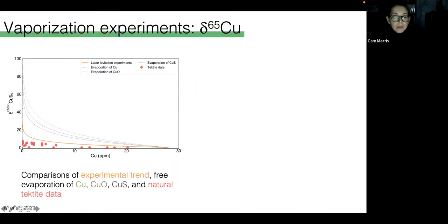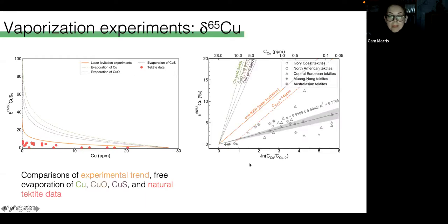So now I'm showing you again copper concentration on the x-axis versus delta 65 copper on the y-axis. You've seen all of these data before, I'm just comparing them. So now the experimental data is represented by this orange curve. The red circles are natural tektite data. And then these curves here are those theoretically predicted Rayleigh fractionation curves. And then on the right, I'm presenting the exact same data, but again, I've manipulated these axes. So now the x-axis is the natural log of that fraction of copper remaining. And here, these are the theoretical lines that are these lines over here. Here are our experimental data, and then here are the natural tektite data.